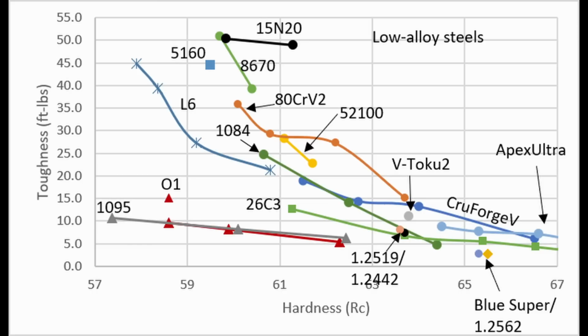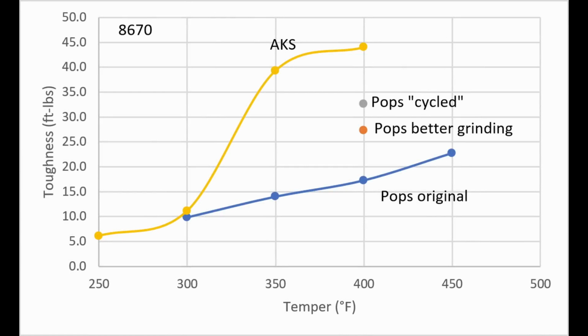In early studies of 8670 with some steel that came from Alpha Knife Supply, heat treated by knife maker Warren Kryko, and then I machined the specimens and tested them, we got really high toughness, close to that of the 15N20 that we just discussed. But then I did another study on 8670 along with Pop's Knife Supply with their 8670, which comes from a different source, though neither company says which steel company produced the original steel. And the toughness was significantly lower than our original Alpha Knife Supply steel.